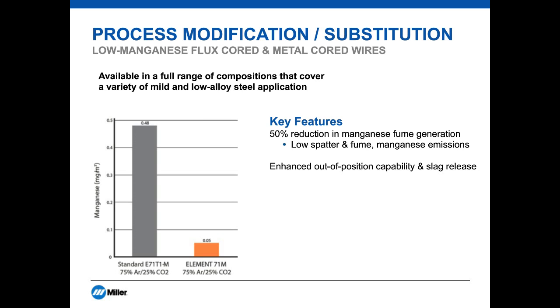Another option is to choose a filler metal that targets specific constituents in the welding fume. This graphic gives a comparison of manganese exposure using a low manganese flux cord wire versus a traditional flux cord wire. Reductions in manganese exposures of 50% or more are possible with these low manganese filler wires. You should note that the testing shown here was done in our test lab under controlled conditions. You should always do exposure testing in your own facility to verify results due to the large number of variables that can affect fume exposures.